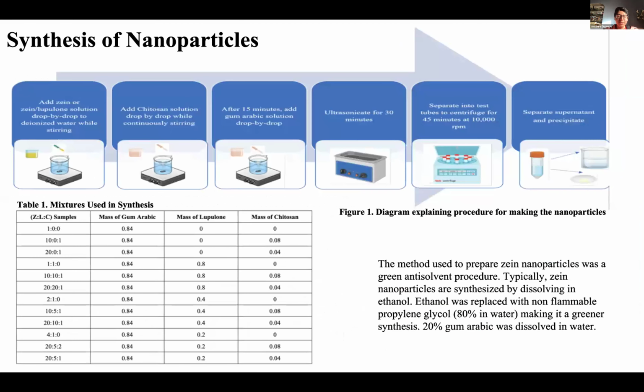So these were the steps we took to make the particles. You start by having the deionized water in the beaker under continuous stirring. You slowly drop in first the zein, followed by the lupulone, and then the chitosan in the same way. After letting that stir for 15 minutes, we added the gum arabic solution drop by drop, which would then precipitate out the nanoparticles. Our solutions we then transferred to an ultrasonicator, which would ultrasonicate for 30 minutes to help dissolve everything.